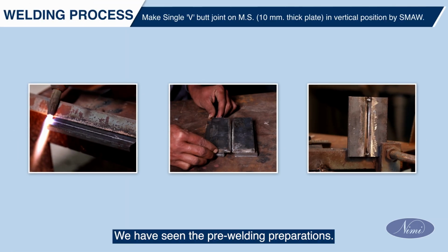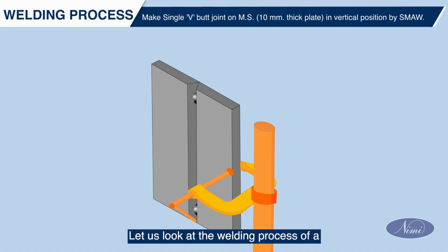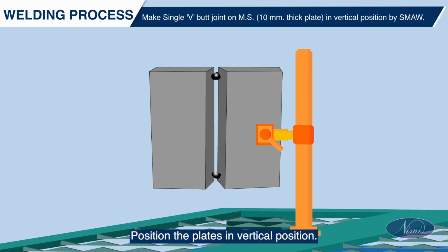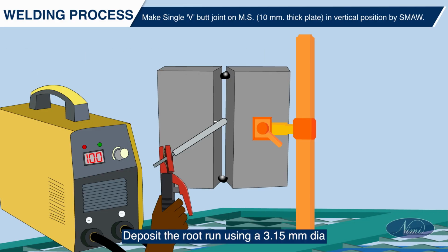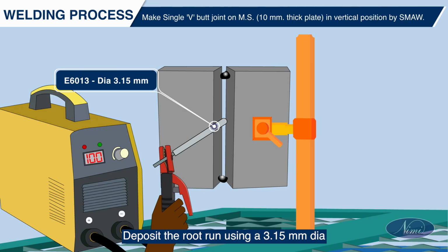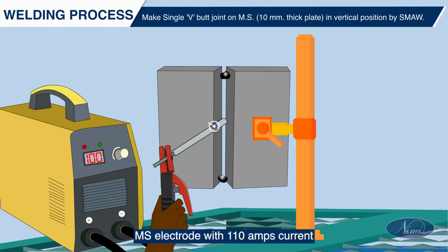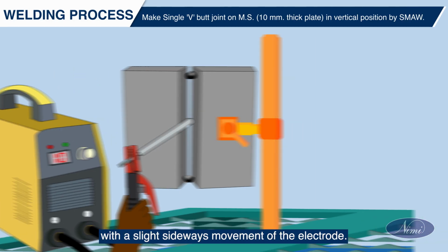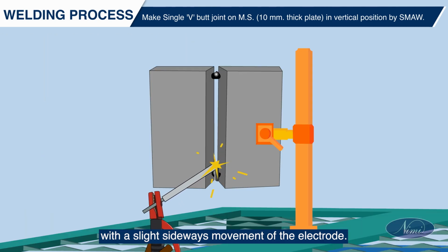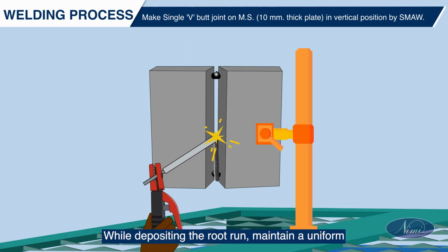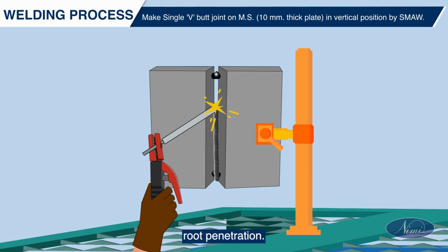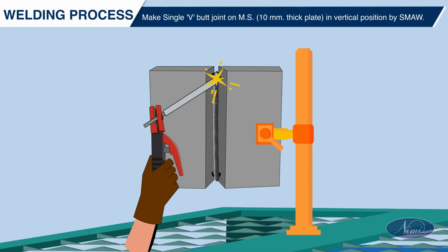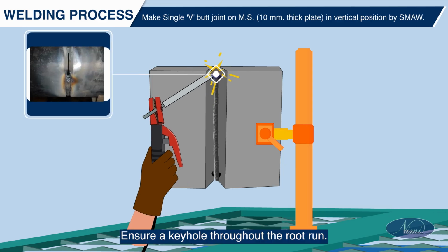We have seen the pre-welding preparations. Let us look at the welding process of a single V butt joint on a 10 mm thick MS plate in vertical position using the SMAW process. Position the plates in vertical position. Deposit the root run using a 3.15 mm dia MS electrode with 110 amps current with a slight sideways movement of the electrode. While depositing the root run, maintain a uniform root penetration. The arc length should be short. Ensure a keyhole throughout the root run.